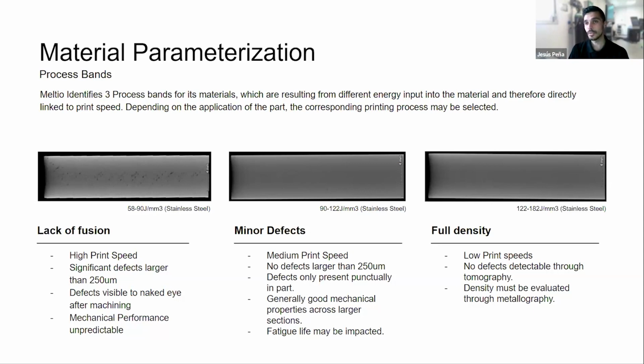That is where a lot of companies work, knowing that they are always going to achieve this 99.99 density. In here, you will not detect appreciable defects, and actually the density is evaluated through metallography, and those are the bands where we make the majority of our mechanical tests. Usually, we don't focus on the minor defects or lack of fusion. When we want to get the best mechanical properties, we always go with the fully dense parameters and we test what we achieve. We have also done it with minor defects and so on for our utility profiles, for knowing exactly with big deposition rates what properties I'm able to get.